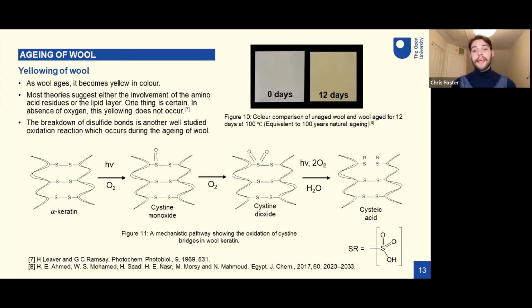Now, I've just represented it as SR for ease, but as you can see in the bottom right-hand corner, this SR is actually the sulfur that's bound through the amino acid to the protein. And then it also has two oxygen atoms bonded with also a hydroxyl group, which is this OH group, an alcoholic group. And this is significant because, as I mentioned earlier, disulfide bonds are really strong and provide some structure for the keratin. In reality, I think the yellowing of wool, the reaction that is responsible depends on the aging, and it's probably a combination of all of them.